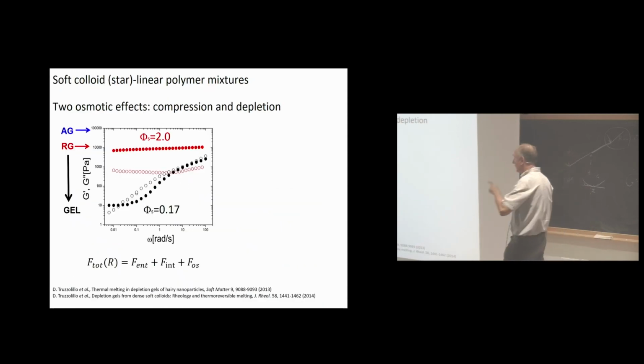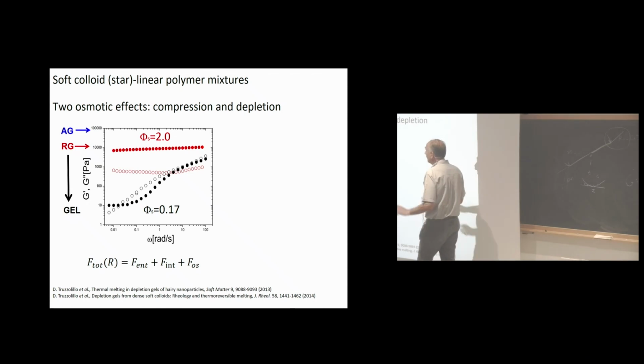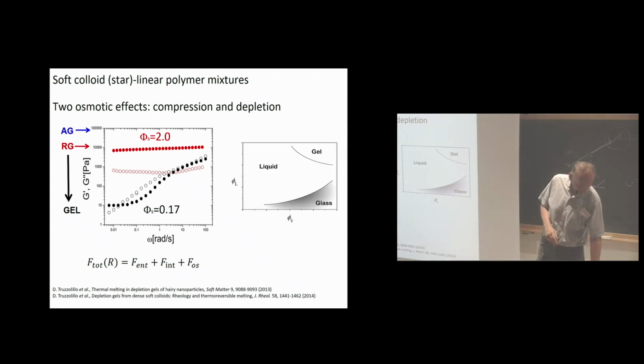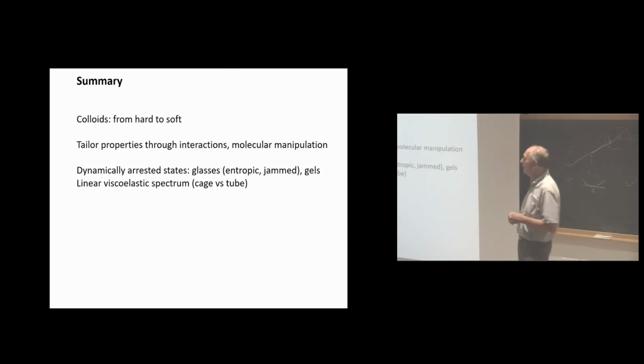If you have, and that's my last slide, if you have softness, okay, sorry, right, so then instead of having a re-entrant attractive glass, because you can basically compress your soft particle, you end up with forming a gel, right? You basically reduce so much the fraction of the soft particles that basically you are in the attraction regime that creates gels. And I'll leave you with a summary.